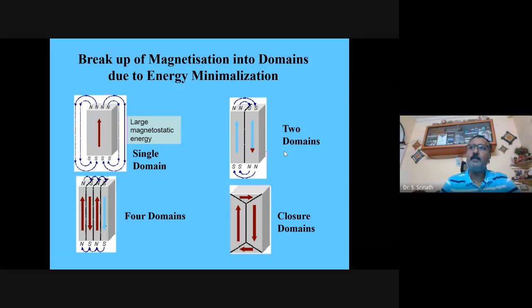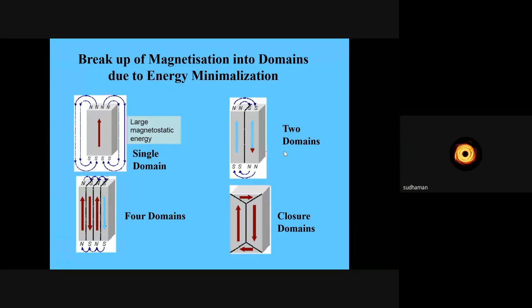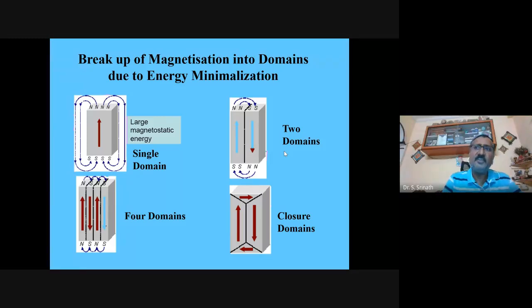Even though they have permanent magnetic moments, they don't talk to each other. They talk to each other only through a field. So when I apply a field, the field will try to align the spins along its direction. Okay, that is how you get a magnetization. But otherwise, if the field is not there, then they are all randomly oriented at any given temperature, thereby giving net magnetization 0. So there is no concept of domain there. To have domains, you need to have interaction between the spins. That's the primary requirement. What holds the spins together? That's the interaction. Okay, so that is what is happening.